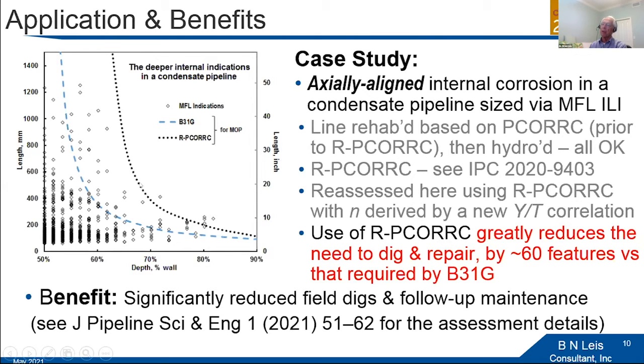This criterion required that certain features be fixed. All of these above and close to it were repaired, and then the line was hydro-tested and passed. So this criterion was proven viable in a real-life application. The bottom line here is that if you look at the number of features that you don't have to deal with using this criterion versus this criterion, this one's accurate, this one's very biased.